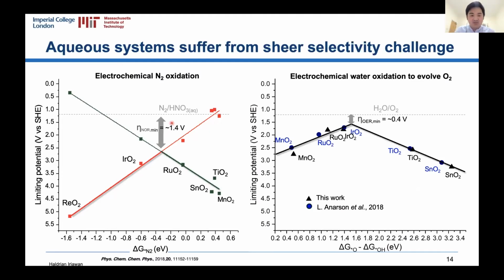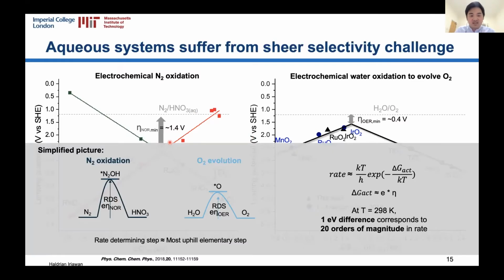We can actually contextualize this by looking at the competing reaction, because in our system we have a lot of water, and this water can be oxidized to form oxygen. So in the competing reaction, we can perform a similar analysis. And we see that at the optimal catalyst, the overpotential is 0.4, which is much smaller than the 1.4 volts in nitrogen oxidation. We can actually quantify this challenge by thinking that for our reaction, the barrier corresponds to this computed bias.